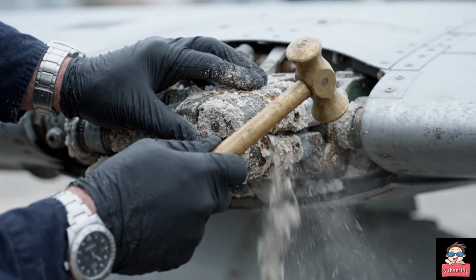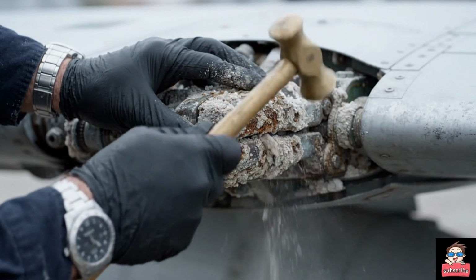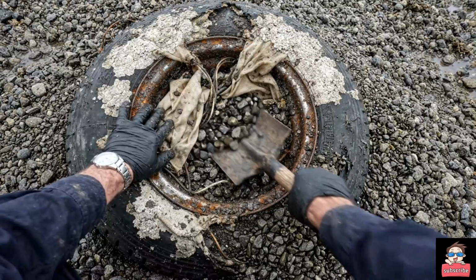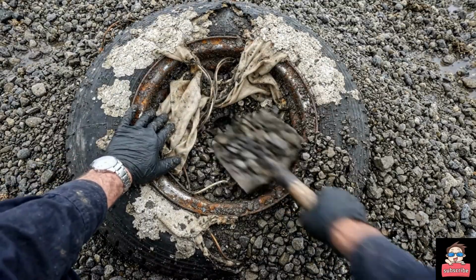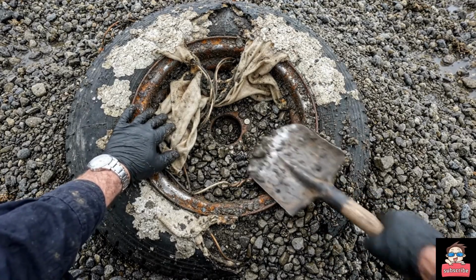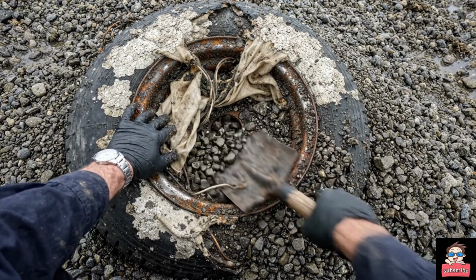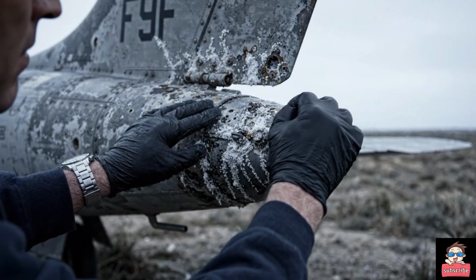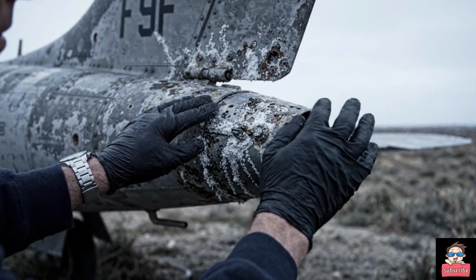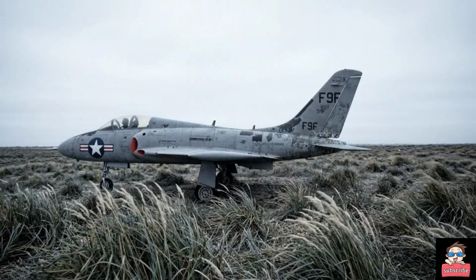The internal pistons are entirely bound up with crystallized sea salt deposits. The nose tire is completely split down to the inner canvas plies. Saltwater has thoroughly dry rotted the classic rubber carcass. The tail assembly acted like a lightning rod for sea spray. The internal hinge pins are completely frozen by corrosion scale.